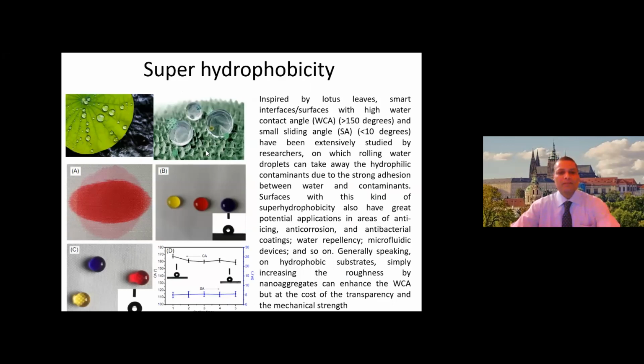Another interesting feature of nano structure is the so-called lotus effect. If we microscopically analyze the surface of lotus leaf, we see the bars or the projections which are very small, especially a few nanometers, and the distance between two adjacent projections is also less than 100 nanometer, and that enables the droplet of water not being able to be absorbed or spread to the surface. Artificially, if we are able to create such nanostructure on a textile fabric, we are able to have super hydrophobicity, and this is a story of the past. Already we have several super hydrophobic textiles by adopting such features, but this has definitely inspiration from the lotus leaf effect in nature.